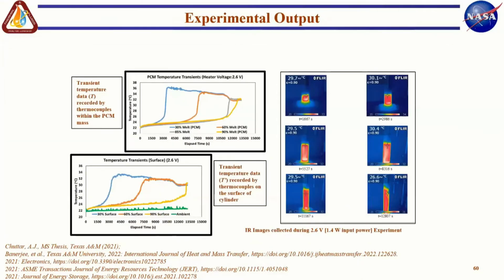So the graph on the top is the temperature time trace by the 3 different thermocouples placed at 30, 60, 85, and then we also put a 4th one at the 90% melt to compare the prediction versus what we measure in reality. The one in the bottom shows the surface temperature trace as well as the ambient temperature. And then the picture on the right shows the IR camera image of the melted PCM as it progresses towards the top of the measuring cylinder. And then we also had a camera recording the location of the meniscus every 5 seconds.